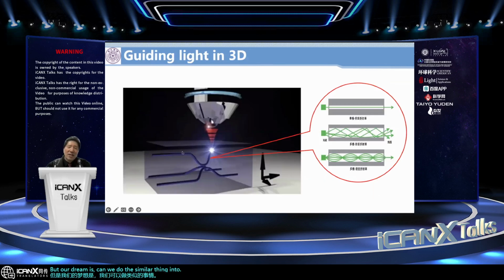Since we can focus light and modify the material performance at different levels, and we can scan the material in this kind of shape, in order to make them guide the light, we can do two things. First, we should reduce the scattering or the absorption in the laser-written part. The second is we should control the refractive index of the laser-written region, so that the refractive index in the laser-written part is a little bit higher than the surrounding. If we can do these 2 points, then it's possible to guide the light in 3 dimensions.